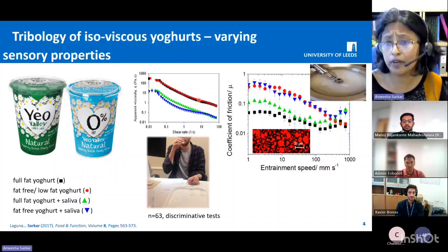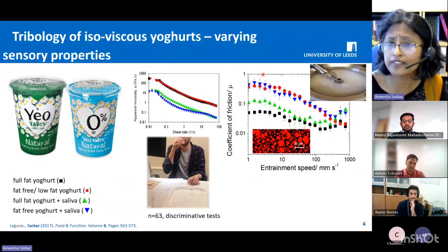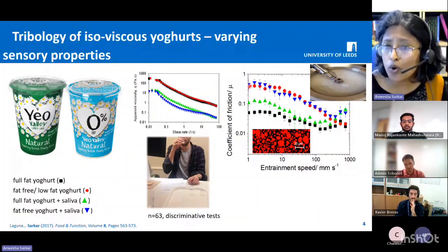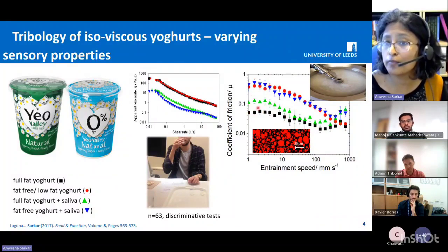So there was no difference that could be explained by the rheological feature. Then we did a tribology. And here you can see an order of magnitude difference. Red is the low fat or fat-free, and the black is the full fat. So an order of magnitude difference in boundary lubrication between full fat and low fat.